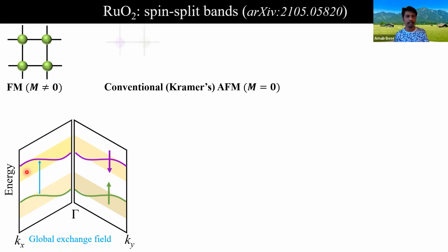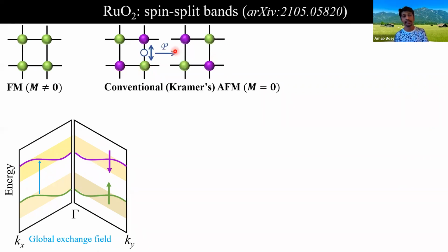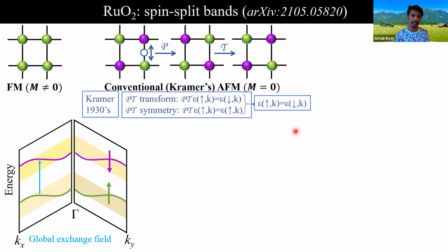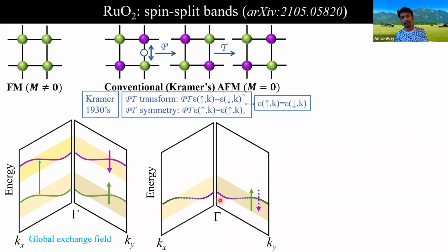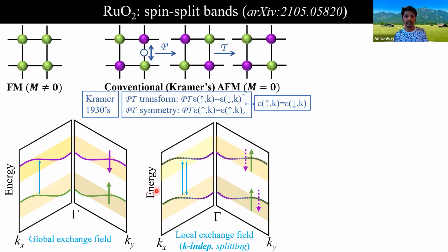Now, let's consider a simple case of an antiferromagnet. Here, I have considered 2 different sublattices. One is up spin, another is down spin. So say the purple one is up spin and this one is down spin. Now, after taking the space inversion and the time reversal, we find this is PT symmetric. And the moment it is PT symmetric, from Kramers' theorem, it guarantees that it will have spin degenerate bands. And now, due to the local antiferromagnetic ordering, we'll have another set of bands at a higher energy level. But still, we cannot have spin non-degenerate bands as a function of k. So this is all standard for the regular collinear antiferromagnet.